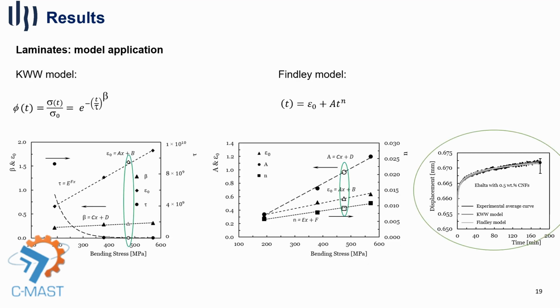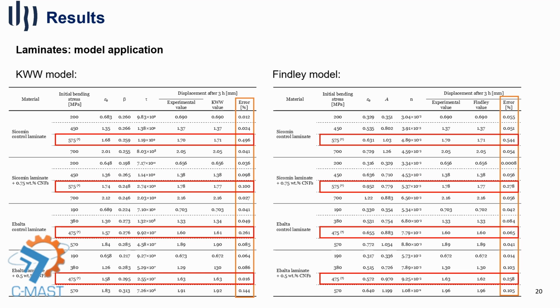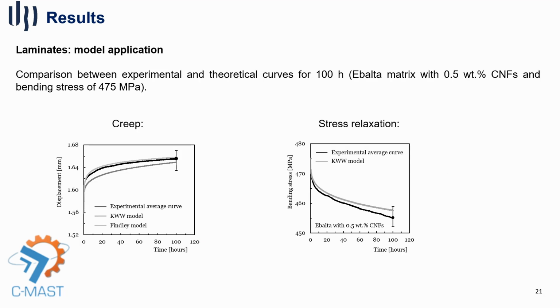The same models were applied, obtaining theoretical results within the dispersion of practical results, and errors compared to the practical results kept low. The tables contain the parameters calculated and estimated by the two models for the different loads studied, as well as the theoretical and experimental values after 3 hours and their respective errors. As we can see, by applying the models, it is possible to provide creep and relaxation results close to the theoretical results for longer periods of time, for example 100 hours.